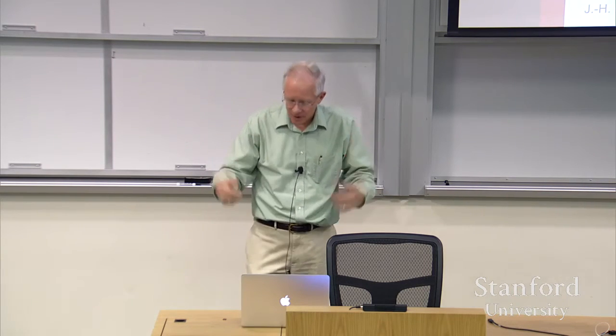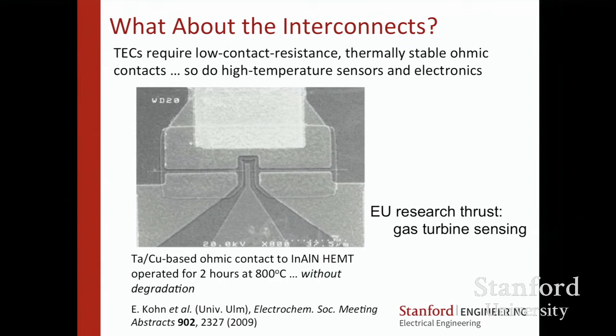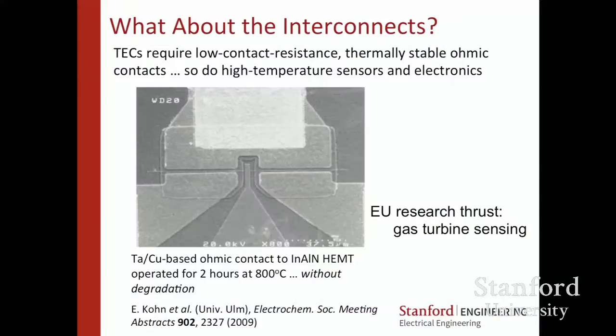Now, in much of my career, the core device is always wonderful, but if you pan out, you have wires. And interconnects and contacts are the bane of everything. So are we actually having something that's great, but you can't actually get any current out? Well, it's nice that other people are trying to go to very high temperatures. The EU has had a big project on high temperature gas turbine sensing, and we have a colleague, Debbie Senesky, in Aero and Astro, who is very motivated by Aero and Astro applications where MEMS sensors have to go to outrageously high temperatures. So here's an example of an indium aluminum nitride HEMT that's been running at 800 degrees.